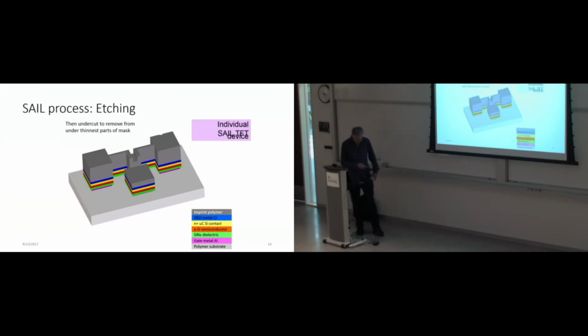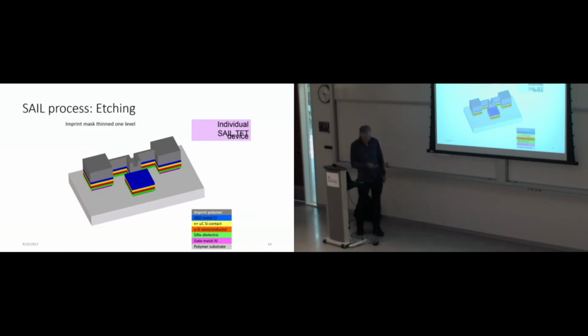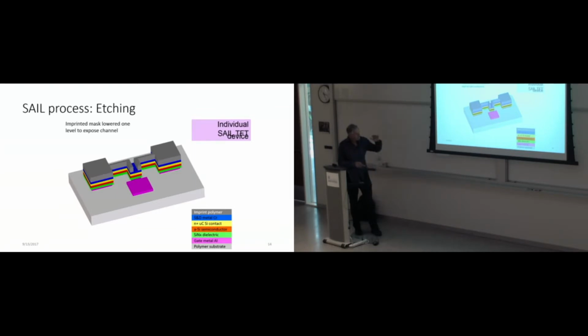We now lower the level. We're using the level information now. So we've uncovered this, and we can now work on this, but the rest of it is still more or less covered. You will have some little undercuts, and that limits what spatial resolution we can get for our imprint lithography. It depends on how controlled your undercut is. But anyway, now the gate pad is exposed. Now we do another lowering, and we've now exposed the channel region.